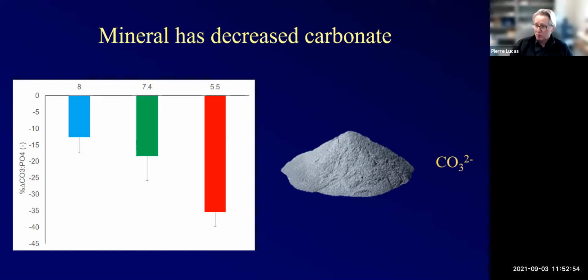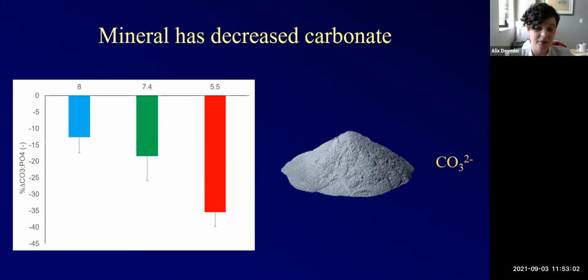Is it something you would maybe do, or do you think it would give you more realistic results? I mean, when we do it on the bones, that's essentially what we're doing. With the bones, it's a little tricky because once you start crushing them, once you start modifying the bone, it gets harder. So doing X-ray diffraction, which usually requires a powder, is very difficult on whole bone. But we have done lots of synchrotron on whole bone where we can get lattice structure.